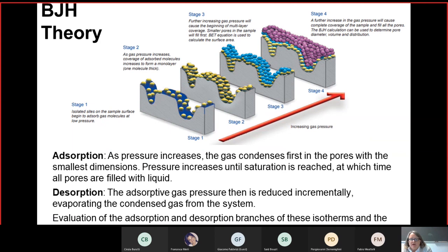I don't think I have it in a slide, but one of the things that is important, I told you that pores come in many sizes and many shapes. And so when you do this sort of analysis, you make an assumption about the shape of the pores. I've done some things where I assume it's cylindrical, and then maybe I assume it's spherical. Not a big difference, but it is something you're assuming. It's an approximation when you do this, but it gives some good information, particularly comparatively.